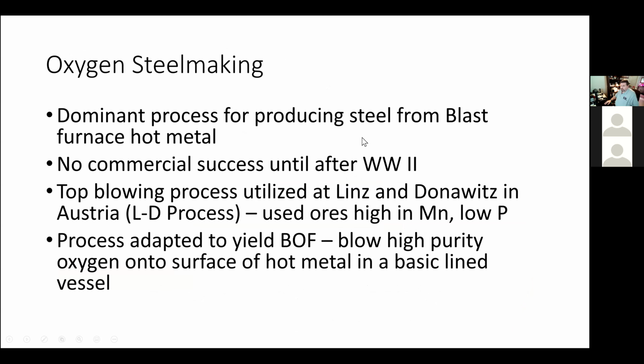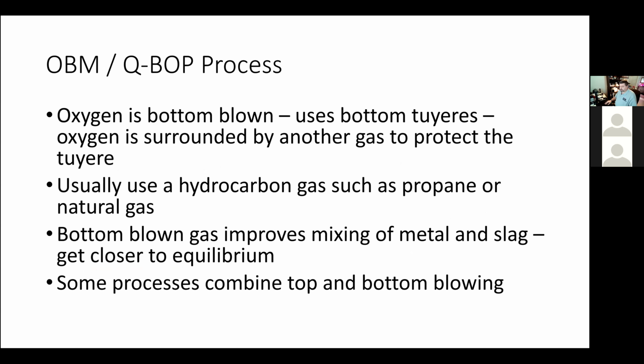So oxygen steelmaking, the history is that it really didn't have any commercial success until after World War II. There was a top-blowing process utilized at Linz and Donawitz, two plants that were run by voestalpine. And as a result, this was called the LD process. They were typically using ores that were high in manganese, low phosphorus. And in North America, we adapted the process to yield what we call the BOF. We're blowing high purity oxygen onto the surface of the hot metal in a basic lined vessel in order to convert the hot metal into steel.